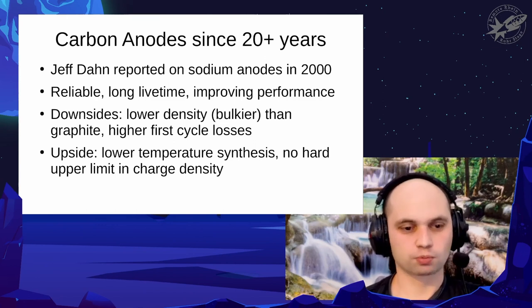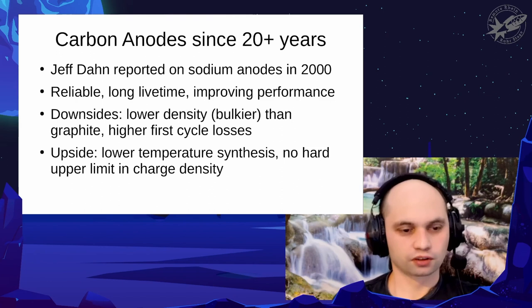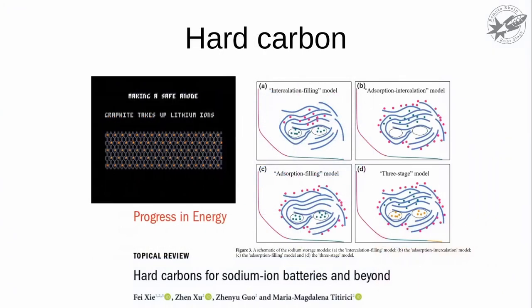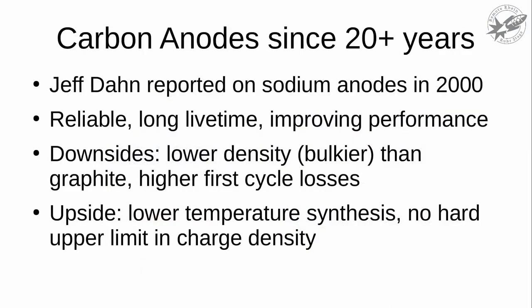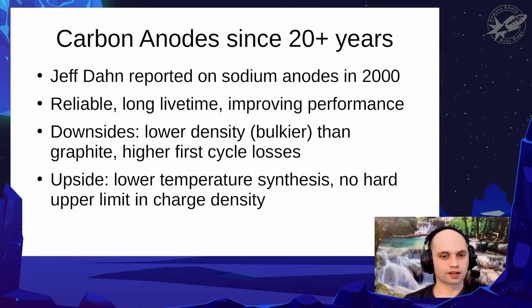Nobody really has any problems with carbon except for some of the performance issues, like lower density. It doesn't have the same density as graphite because it's not very ordered, whereas graphite is neatly stacked and very well ordered, so it has higher density. The hard carbon does not. And you also get higher first cycle losses. This has been improved recently, but it's not quite up to the standards of graphite. With graphite, you lose about 4 or 5%. With hard carbons, it's more like 10% or so. It used to be 20%, and that's a major reason why the current batteries from CATL are much better than the Sharp Labs batteries.